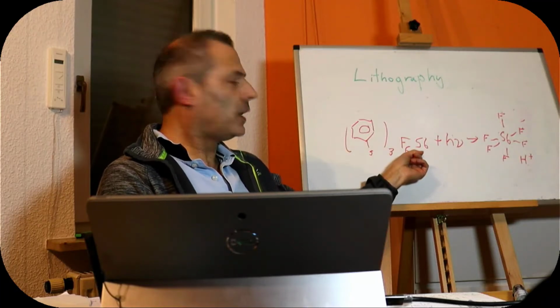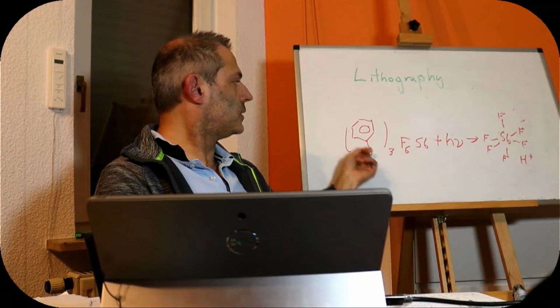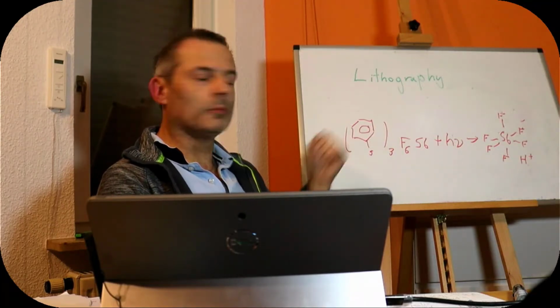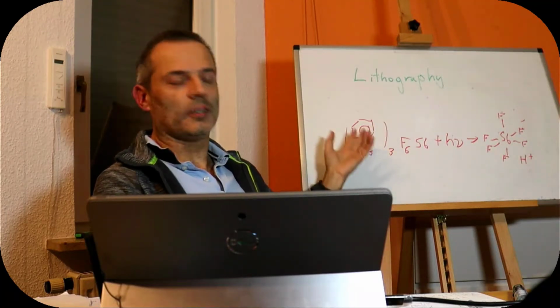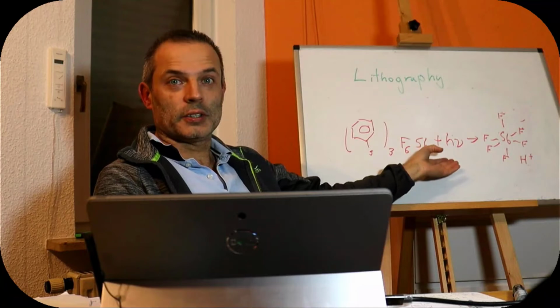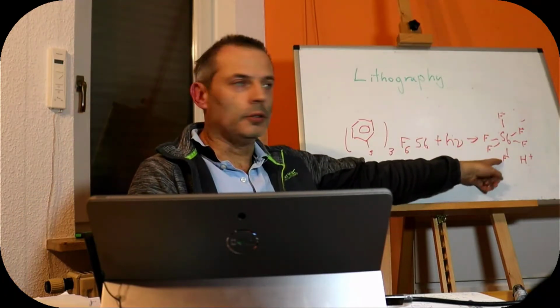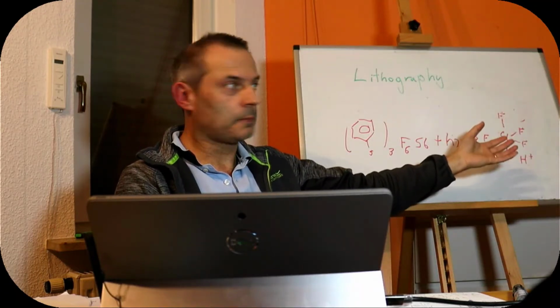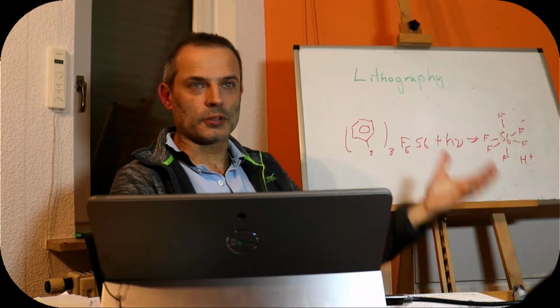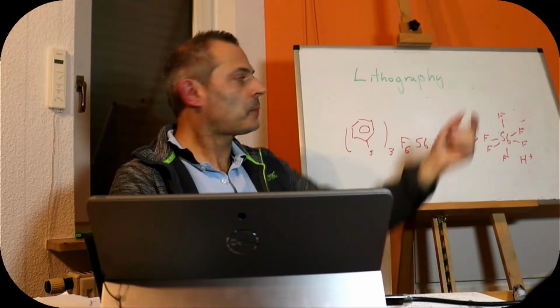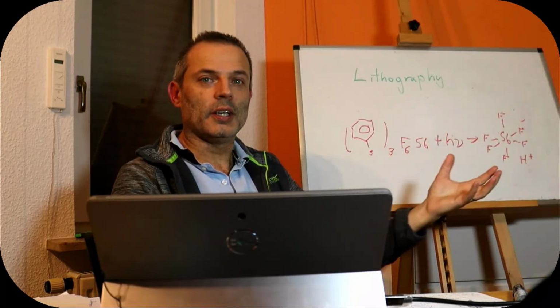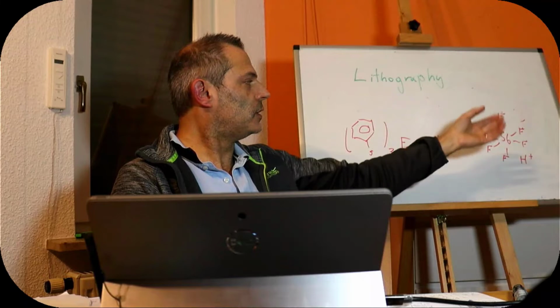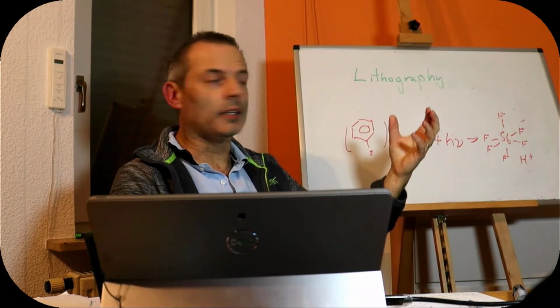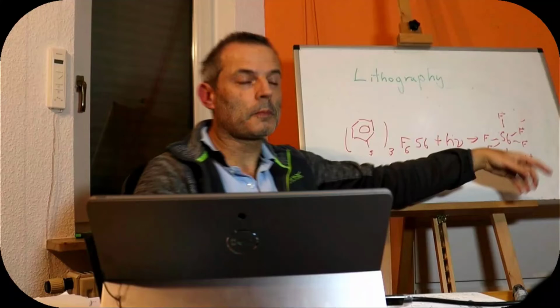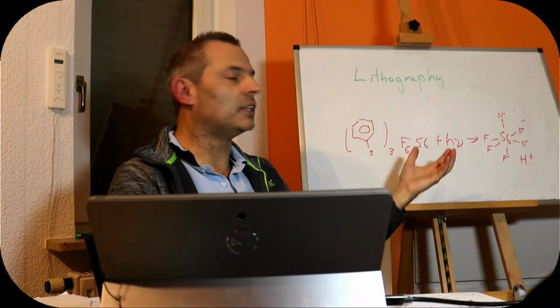We have a strange antimony salt, an antimony fluoride, that's connected to these strange ligands, the sulfur benzene, so there's benzene sulfide, and we excite it with some light, and that generates this new species, which is hexafluoroantimonic acid. As we can see, so going back to hard and soft, and the acidity of things, as you can see, the hexafluoroantimonate ion is extremely stable because it's extremely large. The negative charge on the fluorine is very stable, and the antimony is happy in the middle, and that makes it a very weak bond to this proton here, which has the effect that the hexafluoroantimonic acid is unbelievably strong.